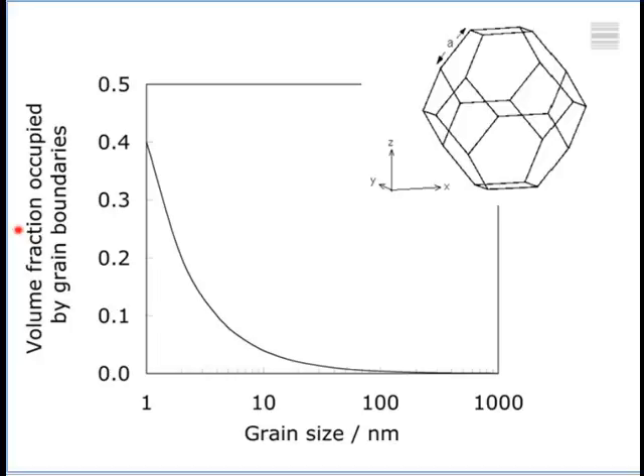So here is how the volume fraction of a grain boundary increases as you reduce the grain size. So if 0.1 of the volume of your material consists of grain boundary, then you're going to have defect-free crystals. That in turn means that there is no work hardening mechanism. Okay, because without defects, you don't have a work hardening mechanism.